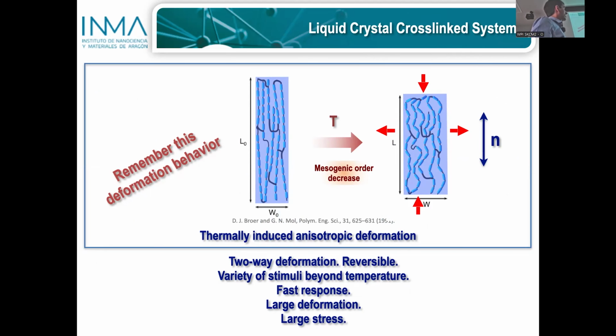But essentially, any cross-linked liquid crystalline polymeric system, when you expose it to temperature, the liquid crystal molecules will tend to orient in a random fashion, as happens with the isotropic liquid. If you heat a liquid crystal, you go to an isotropic liquid. So you get this misorientation, this disorder in the mesogens, but due to the fact that the mesogens are linked to the polymeric network, this will cause a contraction of the material along the director and an expansion of the material in the orthogonal direction. And I want you to remember this deformation rule because it will be very useful in many of the slides later on. So by temperature, we can get a contraction in the director direction and an expansion in the perpendicular direction.